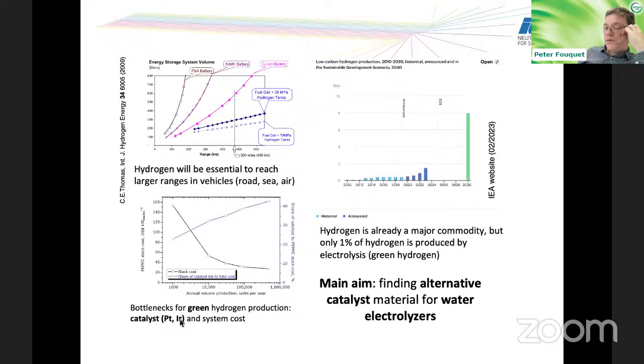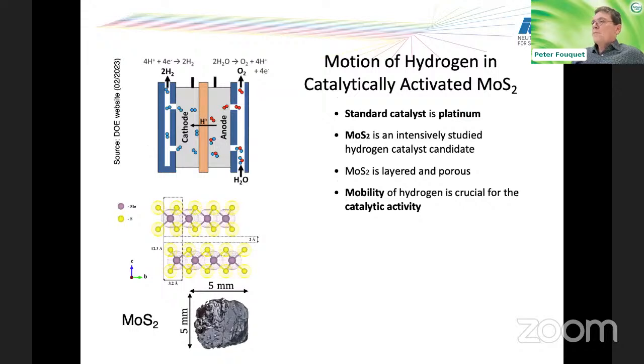And they are, first of all, extremely expensive compared to other materials. And they have to be extracted from the ground, and they are effectively very rare. So if you upscale the production to what would be needed in the future, it's hardly feasible to cover this all with platinum and iridium. So we need to have alternative catalysts. And that's what we are working on. So this molybdenum sulfide that we are working on is a layered material, and it's highly porous. And of course, there have been studies on the structure, but about the mobility of the hydrogen in this material, very little is known.